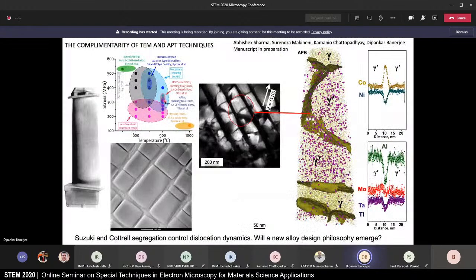A second example is at higher temperatures and high stresses. And at these combinations of stress and temperature, you again have shearing of the Ni3Al, but now instead of twinning, the shearing results in the formation of anti-phase domain boundaries. And it is extremely difficult to look at segregation at these faults because the faults are curved through TEM, because TEM always provides you with a projected structure. And so here's an example again of atom probe tomography. So this entire area here covers in atom probe tomography this area over here. This antiphase boundary is imaged over here in atom probe tomography. This is the matrix over here, and this is Ni3Al. And again, you can see the segregation quantitatively of various alloying elements in this alloy to these faults.